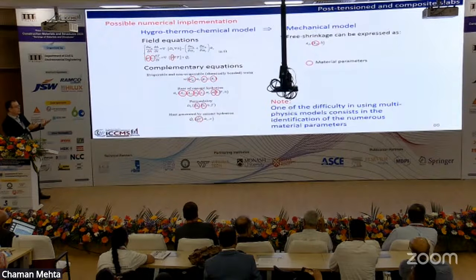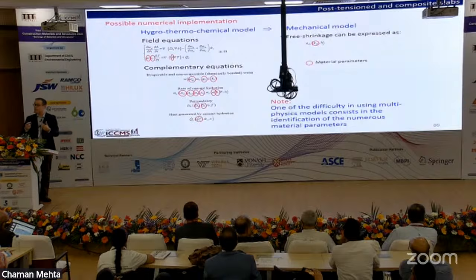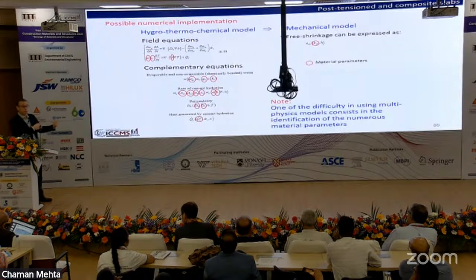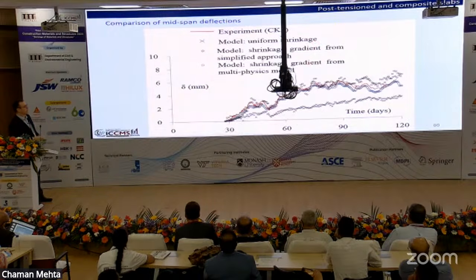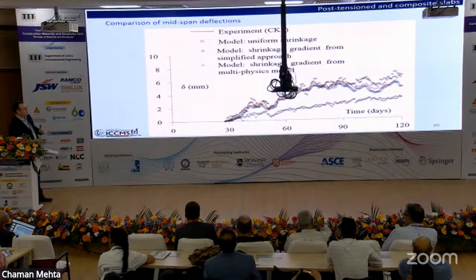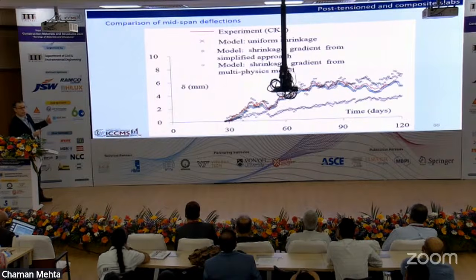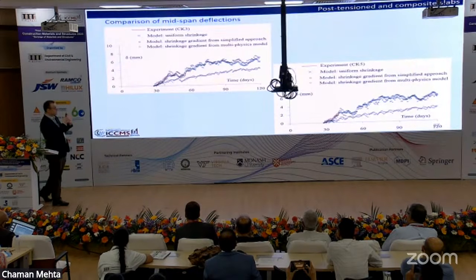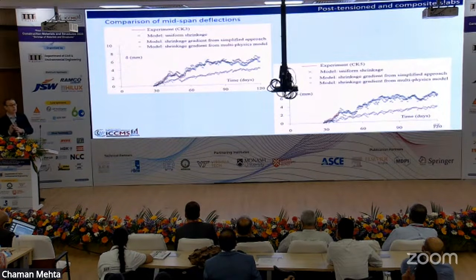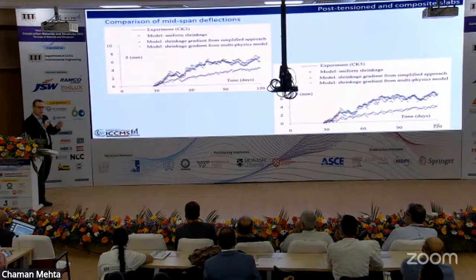Because when you have so many parameters, you actually have different sets of parameters that will give you the right solution, or the solution you measure. So I would say the challenge is really there. And it's just to show you how, with this sort of multi-physics model, we were able to identify the parameters just for the concrete mix, and then we're able to capture quite well the response. So I would say this is where I would love, at least, future trends in our standards to move, to push them to really move over to multi-physics heavily. And again, a similar trend. And these are not numbers that we fudge. That's what's beautiful. They're parameters we identify through a particular process.